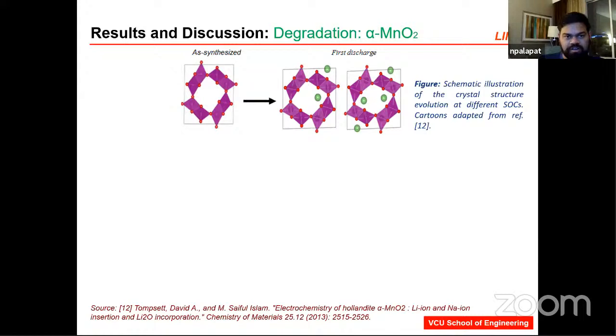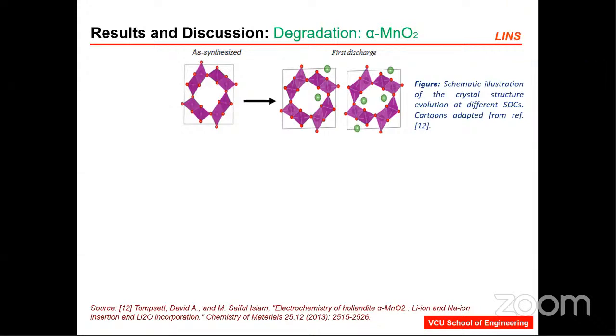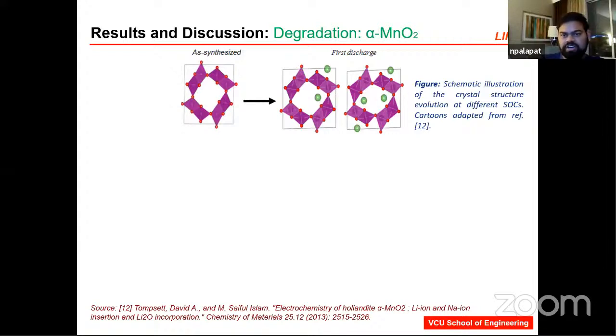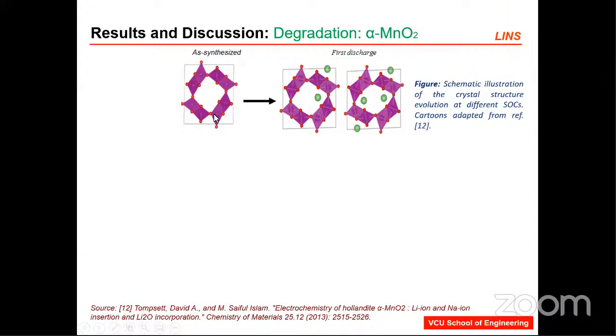It has this gap in the crystal structure, and when you do the first discharge, where the lithium ions come and sit in the cathode, the lithium tries to occupy the lower energy tunnel walls in the crystal structure. The crystal structure started with this, but after the first discharge, the lithium ions occupy equal spaces, the lower energy tunnel surfaces inside the crystal structure. This contributed to an increase in the mechanical strength of the material compared to the original material.